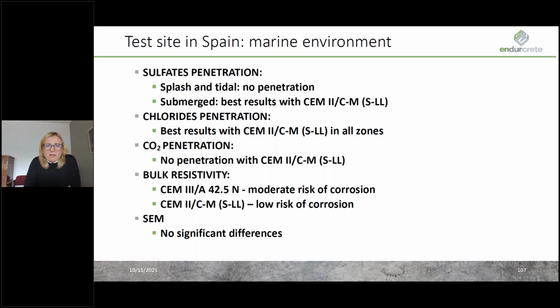So in summary, no sulfates penetration was recorded in splash and tidal zones, and in the submerged zone, the best results were with EnDurCrete concrete with CEM2 CMSLL. The same was for chlorides penetration. The better results were recorded with the EnDurCrete concrete in all zones, as well for the carbonation. The bulk resistivity showed a moderate risk of corrosion for the reference cement and very low risk of corrosion for the EnDurCrete concrete. And in the SEM scans, there were no significant differences.